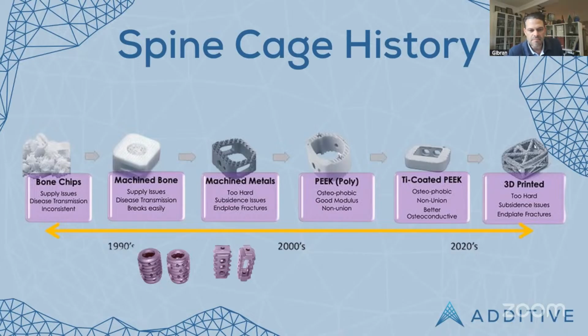Then PEEK cages became coated with titanium and plasma sprays, because PEEK inherently is hydrophobic. Bone protein doesn't grow on it very well. Bone doesn't grow onto the material very well. So coating PEEK cages with the titanium spray helped address some of those challenges. More recently, we've seen the rise of 3D printed titanium cages. Now, titanium's fantastic because it's the reference material for biocompatibility. But with 3D printing, we can really dial in some of the nuances of the cage which are important for fusion. The modulus of elasticity is very important, so we can dial that in.